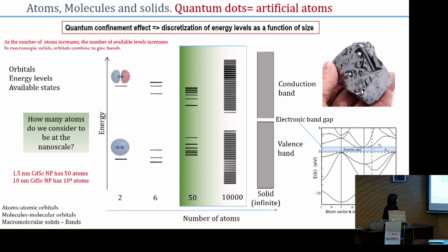So the question is, how many atoms do we consider to be at the nanoscale, for example, for these nanoparticles? So for you to have an idea, a 1.5 nanometer diameter cadmium selenide nanoparticle contains around 50 atoms, while a 10 nanometer diameter cadmium selenide nanoparticle has around 10,000 atoms.